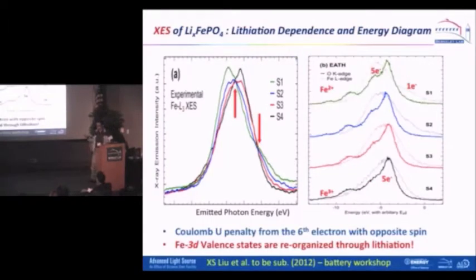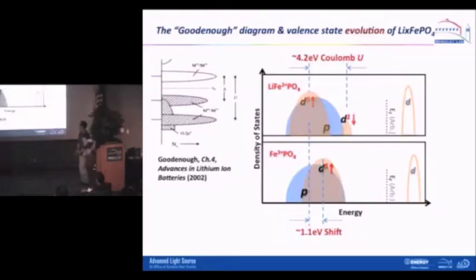And then if we use the same technique on the lithium iron phosphate, what we see is a series of different lithiated lithium iron phosphate. You will see there are two so-called isosbestic points in spectroscopy, meaning there is one state, two state, another state here. And when you align this iron 3D to that oxygen 2P through this hybridization feature, you will get an alignment of this 3D and 2P, and this is the result. So the result shows that when you pull all the lithium out, this is a suspicious status where you have the safety problem.